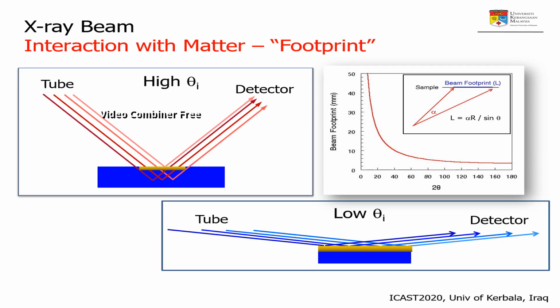It is important to note that due to low incidence angle, the X-ray beam will produce a large footprint. Therefore, it is recommended to have large sample dimensions or to use a knife edge to limit the illuminated area, as shown in the following slide.